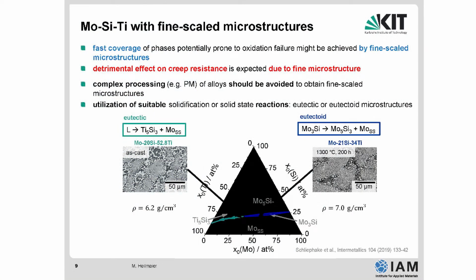And on the other side, you see the blue range, the blue area here. This is a eutectoid reaction taking place. So the liquid first forms a monolithic intermetallic compound of nominal chemical composition Mo3Si, and this later on phase separates into two other phases at lower temperatures, namely the Mo5Si3 intermetallic compound. This looks pretty much similar to the Ti5Si3. However, the molybdenum is replaced by the titanium, and again a molybdenum solid solution. And these are the microstructures which form there.